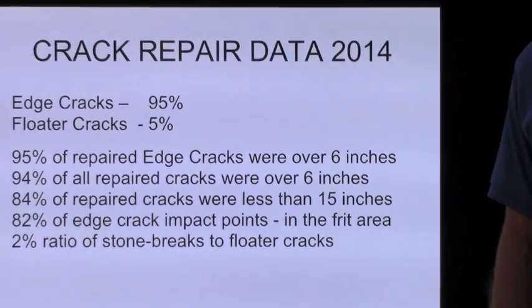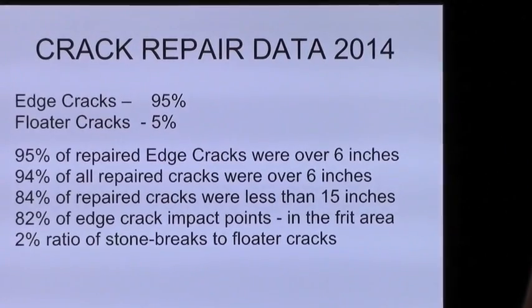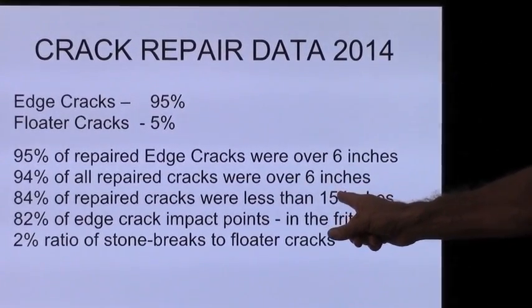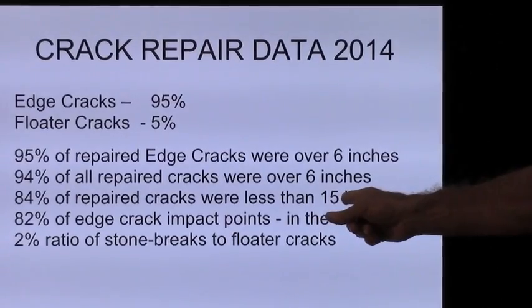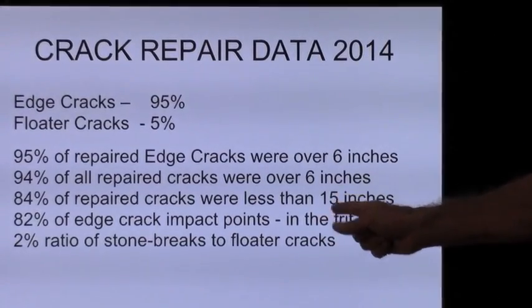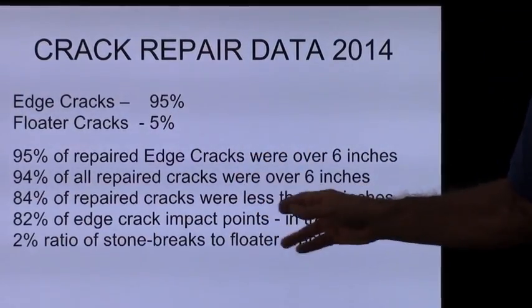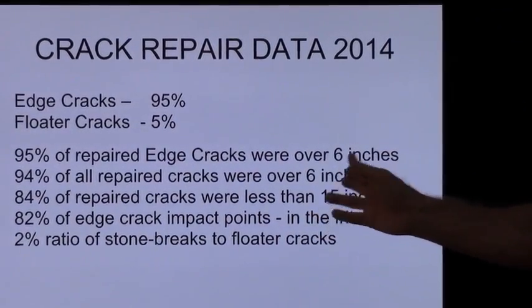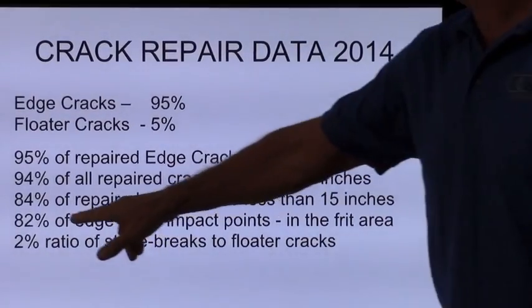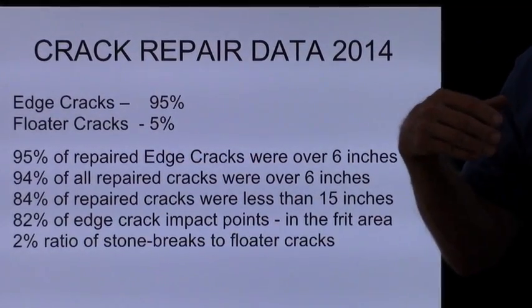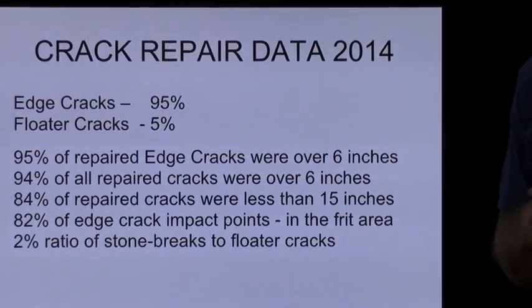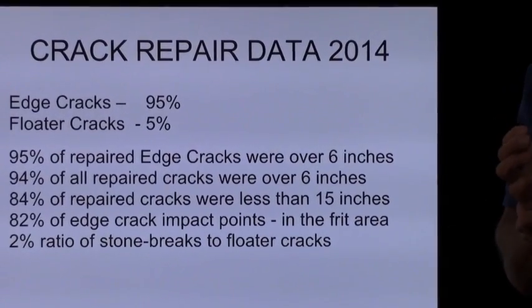That's what the Repair of Laminated Auto Glass standard says, and that is the windshield repair standard in the United States. And believe it or not, we fix them any length because we want to collect data. And what we have found is 84% of repairable cracks are in the repair standard, 15 inches and under. 84%. The correlation is the longer the crack has been there, the more chance it has to become contaminated, and that is the only enemy to whether you can repair a long crack or not.